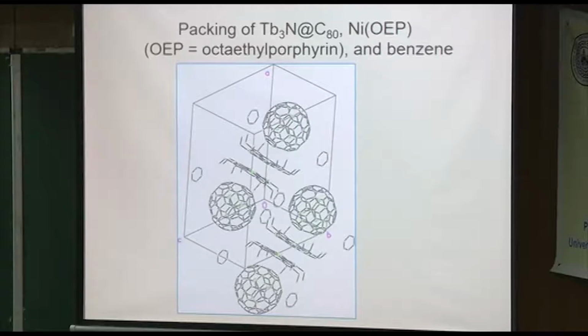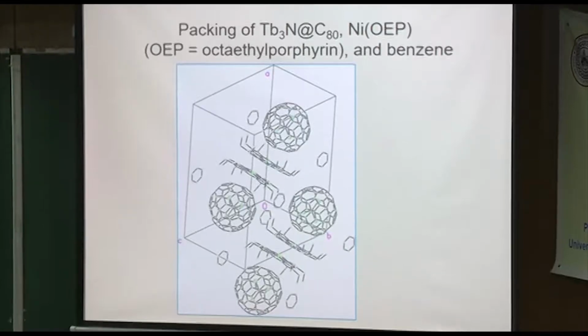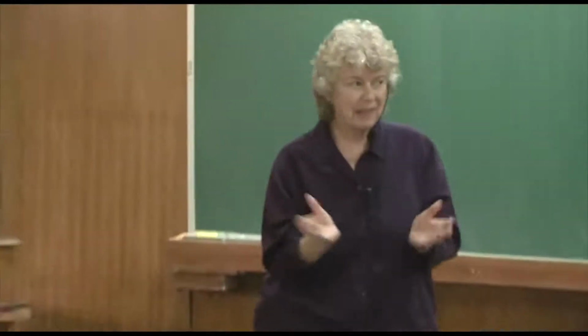The porphyrin, the nickel octaethyl porphyrin, a lot of you know about porphyrins, so I don't need to tell you, it has these arms that can either go like this and like this, or in the case of fullerene, usually both arms will come up and just kind of cup the cage. This is a pi-pi kind of interaction, or maybe a dispersion interaction involving some of the hydrogens on the ethyl arms. But it's apparently very favorable, and actually we discovered this by accident, but it's now been widely used internationally, I have to say, by people who do this kind of research, because nickel octaethyl porphyrin is particularly stable, easy to get.